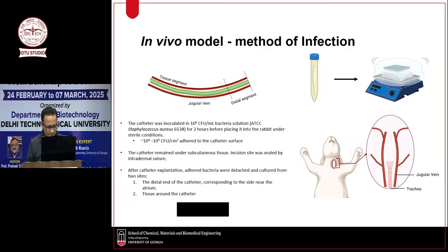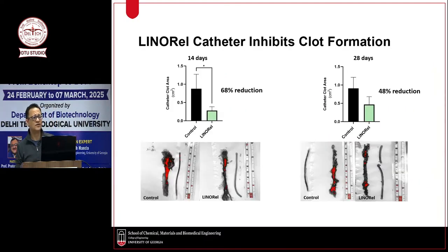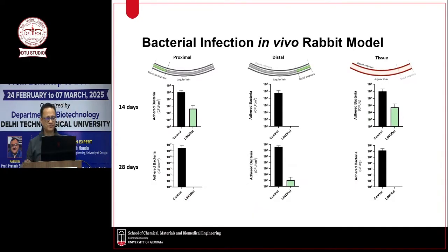Okay, and the beauty is we can get clotting data and infection data, both. So we saw almost 70% reduction in clot formation, and see, that's the vessel we took the catheter out from. And for 28 days, we took some catheters out at 14 days and some at 28 days. Some rabbits were 14 days, some rabbits were 28 days. And we saw 50% reduction in infection or clotting for the 28-day data. This was really good data.